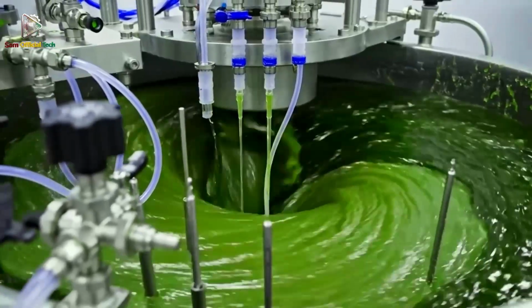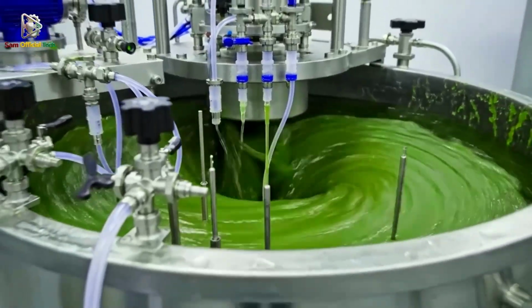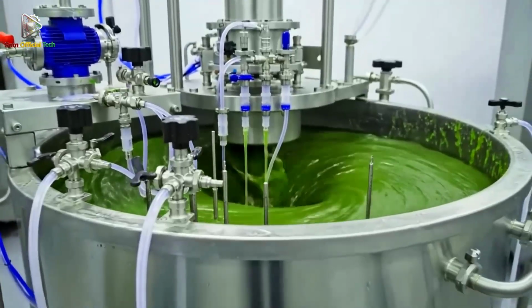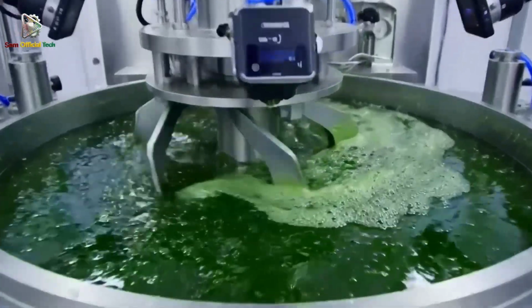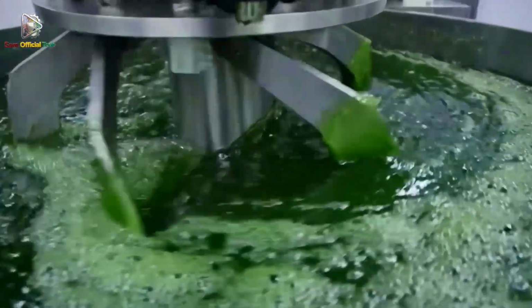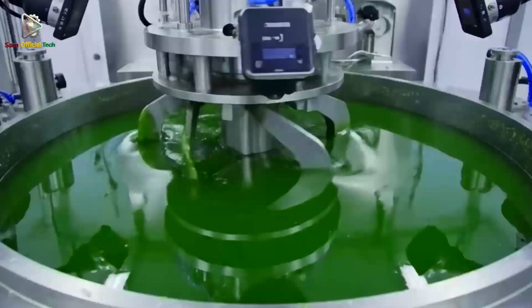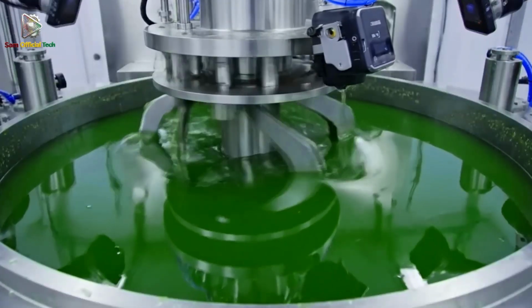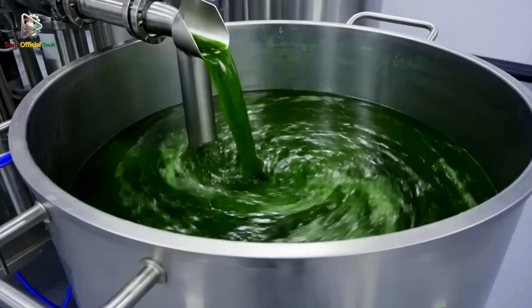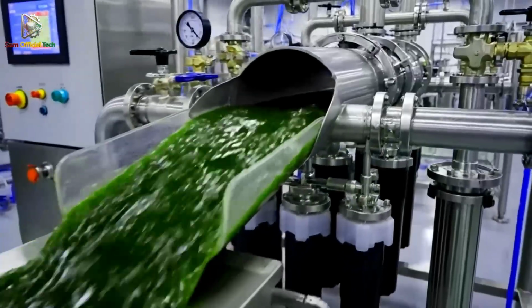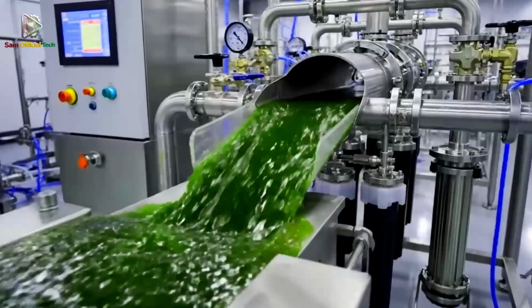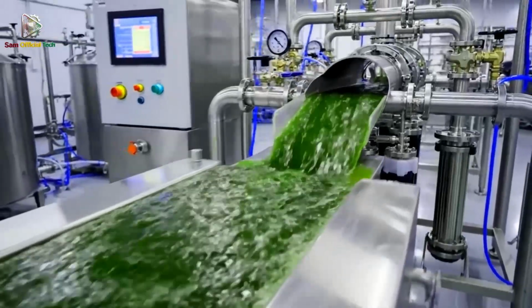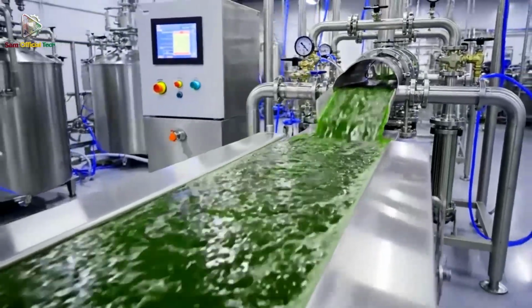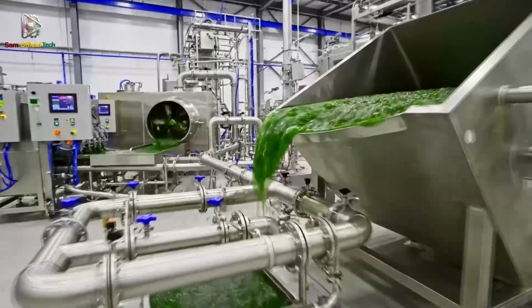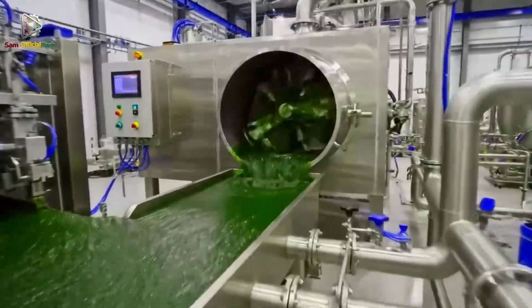Membrane filtration becomes the key technology. Cross-flow ultrafiltration concentrates alginate while washing out salts, small molecules, and off-odors through diafiltration. Cross-flow matters because the liquid moves tangentially across the membrane, reducing fouling and allowing continuous operation. Pressure and temperature are controlled because a few degrees or a few psi can change flux dramatically. And flux stability determines whether the plant runs smoothly or shuts down for cleaning every hour.